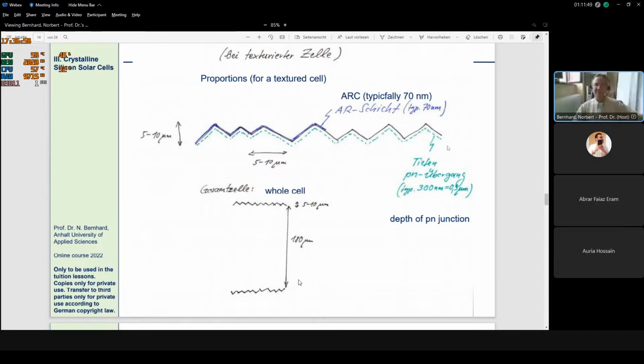And then we deposit an additional anti-reflective coating, which is typically 70 nanometers. The reason is it must fulfill a so-called lambda quarter condition to be very effective. That means the thickness must be a quarter of the wavelength, of which we want to reduce the reflection, in this material. And this is then roughly 70 nanometers. And I said again, this is roughly a factor 1,000 thinner than a human hair. And you see also this anti-reflective coating here in blue. It follows precisely this textured surface.